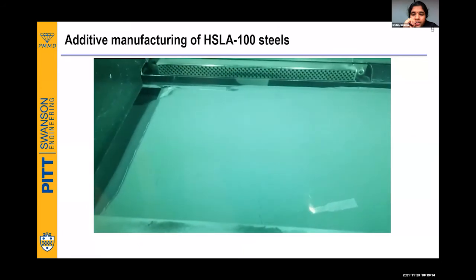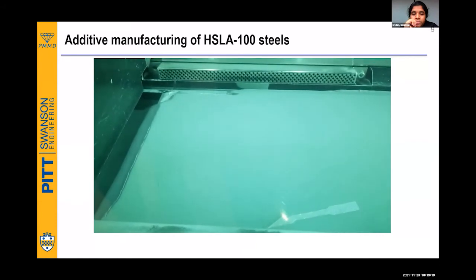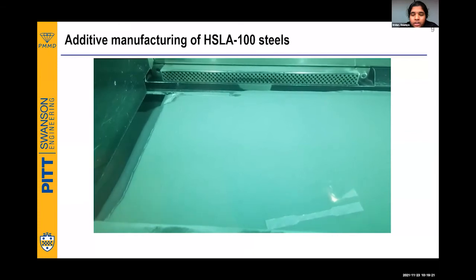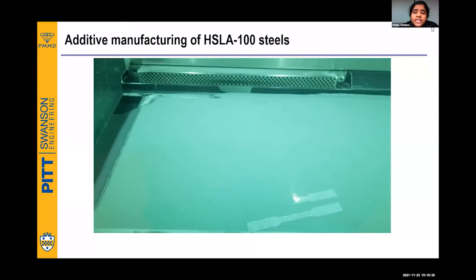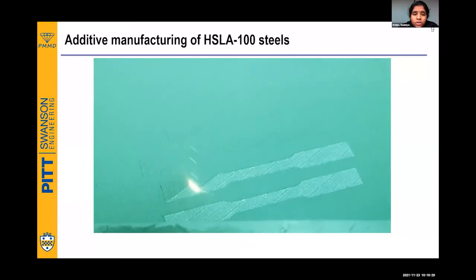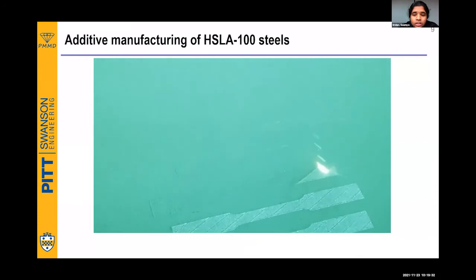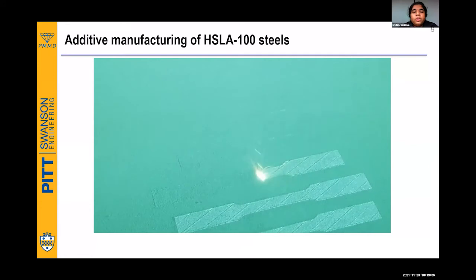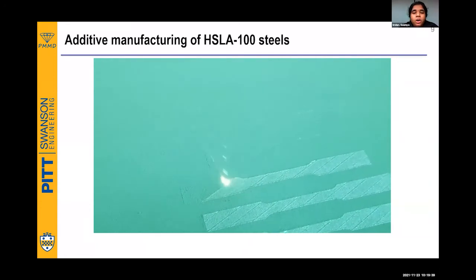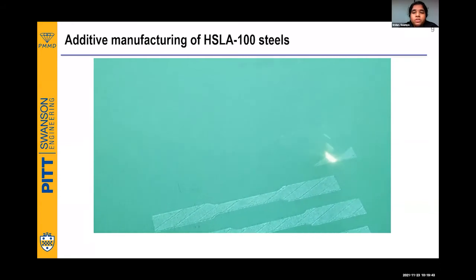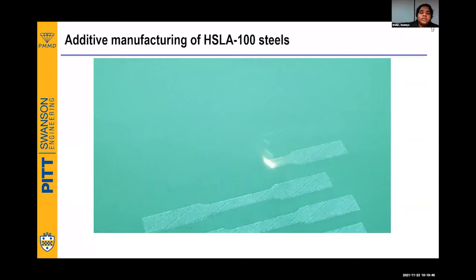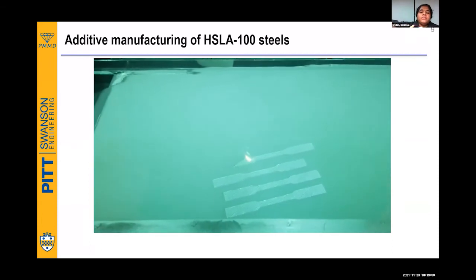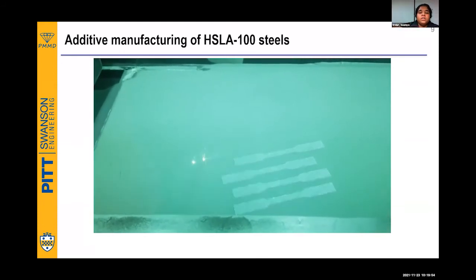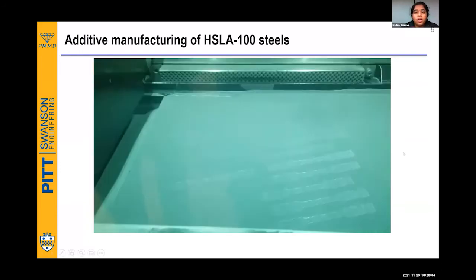We are rotating it, right? Initially the first layer was completely horizontal, and now it is slanting at an angle. Typically we use an angle of 66 degrees. This is done mainly to avoid residual stresses. So in layer 1 the rastering is happening parallel to each other, and in layer 2 we rotate it by 66 degrees. Again layer 3 horizontal, layer 4 66 degrees. We change the scanning rotation for every layer to avoid the buildup of residual stresses.